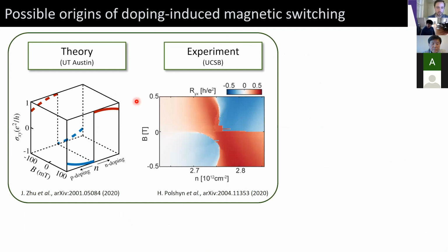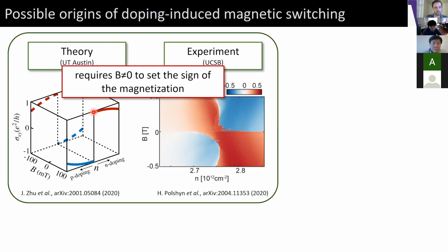Well, doping-induced switching was actually theoretically predicted a few months ago by Allan MacDonald's group at UT Austin, and was experimentally realized in Andrea Young's experiment at Santa Barbara. But this is a somewhat different effect in that the theory and the experiment relied on some finite magnetic field to set the sign of the magnetization. In fact, it shouldn't work at zero magnetic field.